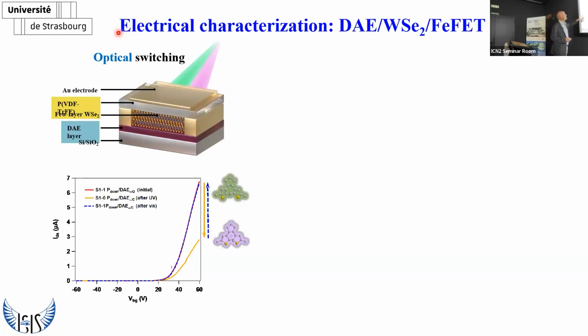So now, the first thing that I was honest in saying before, that I was not sure if I could pass light through all this stack, in particular because the ferroelectric layer is 600 nanometers thick. Okay, so it's very thick. Anyway, it turned out to work, because in this kind of stack we were able to irradiate with different wavelengths from the top and change the state of the diarylethene, such that you can see that we can change by 60% the current through the junction.